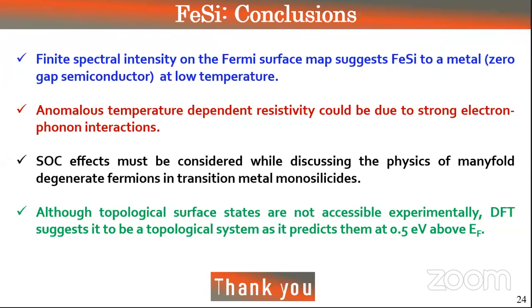But the kind of resistivity that you are getting in the graph which you have shown, resistivity versus temperature, is typical of a metallic kind of range. Because the resistivity of semiconductors is usually 0.1 ohm centimeter or something like that, or higher. But in your case, it is mostly below that range. I agree. That's why I said semiconducting-like profile. I totally agree with you. I could not say exactly this is a semiconductor, but my point was that if it is 35 meV, I didn't see it from such a high resolution machine. Okay.